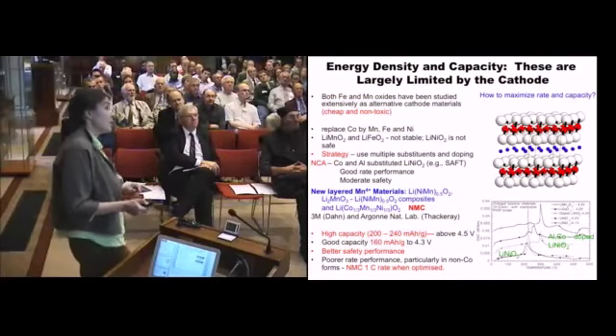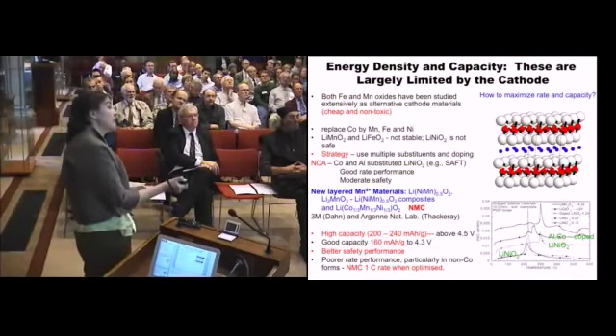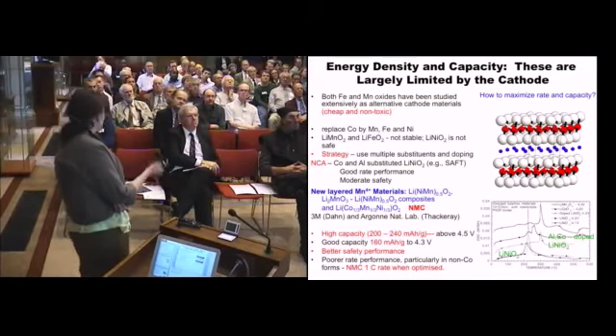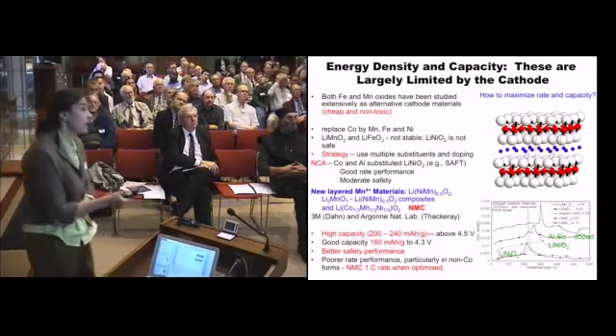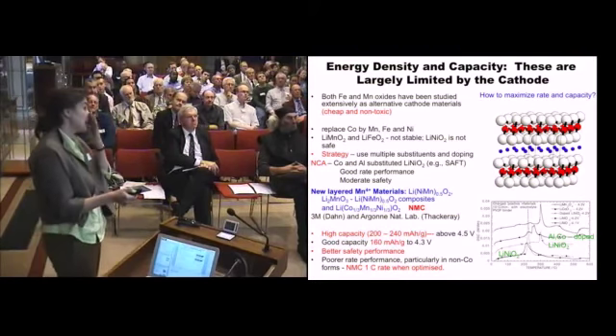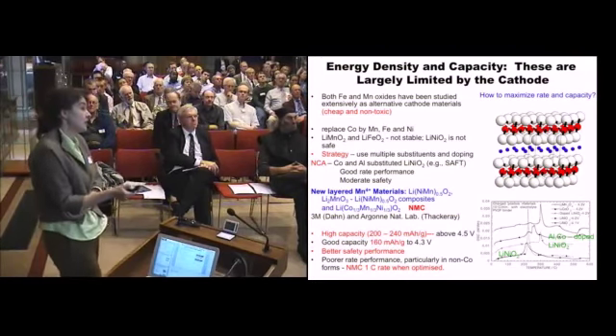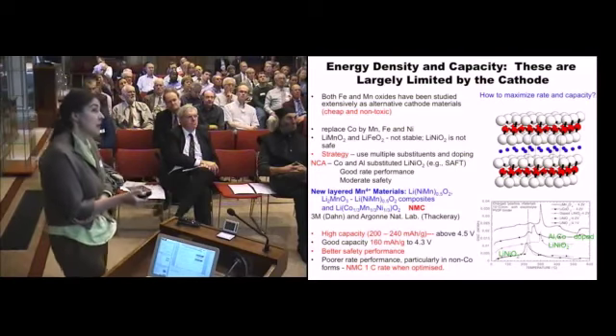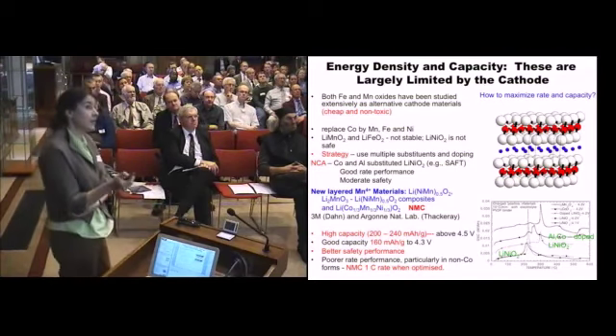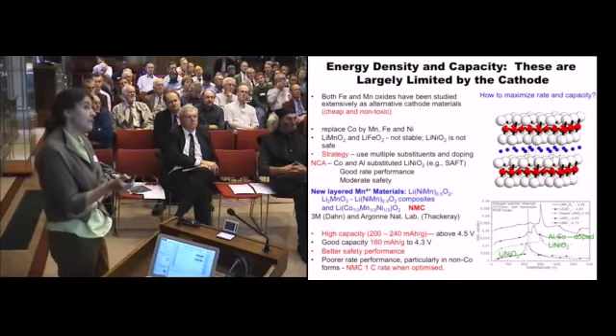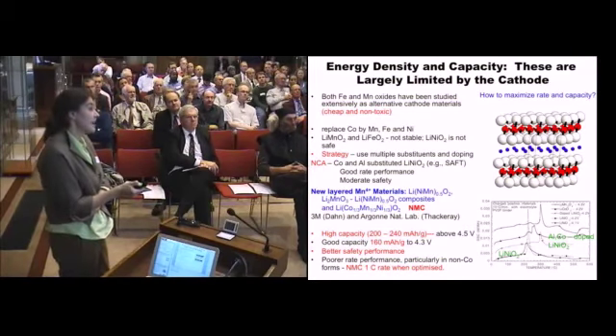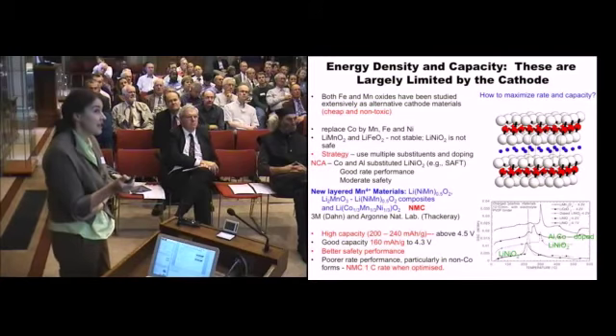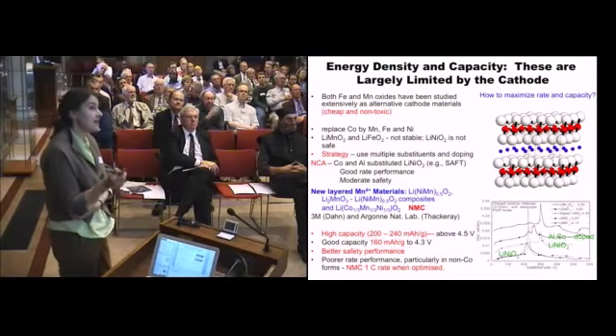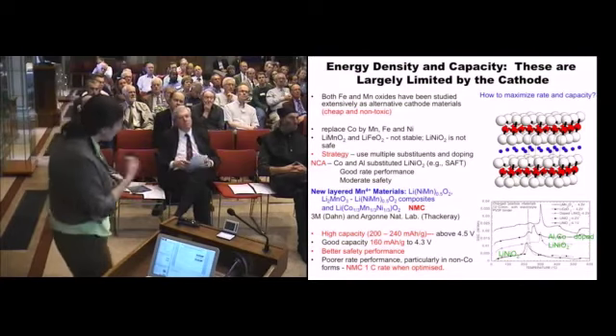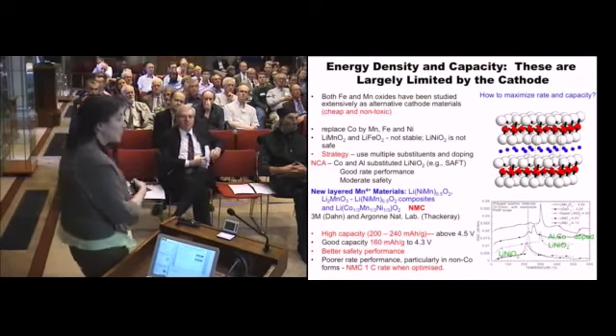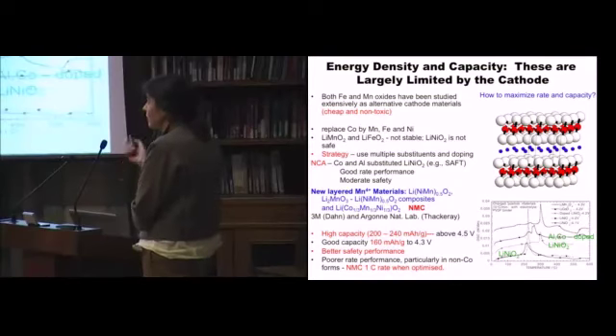So there's been a lot of work over the years in trying to look at different chemistries. And the major emphasis has been on materials that are cheap, materials that are non-toxic. And the only elements that really are effective under those two criteria are iron and manganese. So the first thing that you might think about doing is to take your structure and start replacing the cobalt by your iron and your manganese. But the problem is that you can make a layered lithium manganese oxide, you can make a layered lithium iron oxide, but as you cycle it, it just transforms into a completely different structure, and it's a structure that doesn't like to reversibly remove lithium.